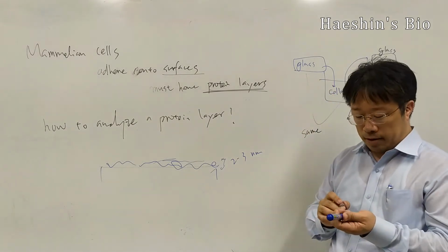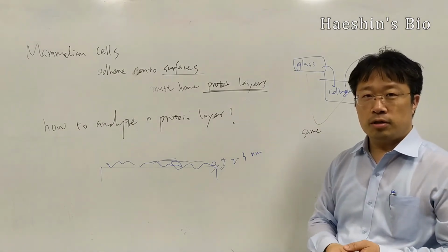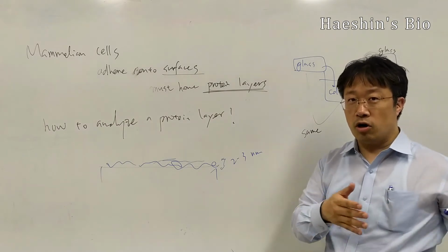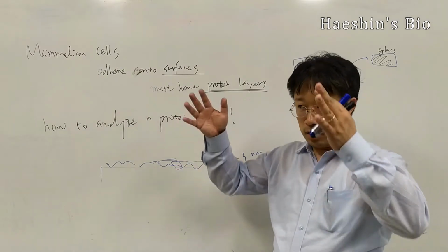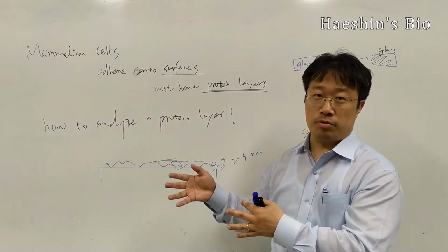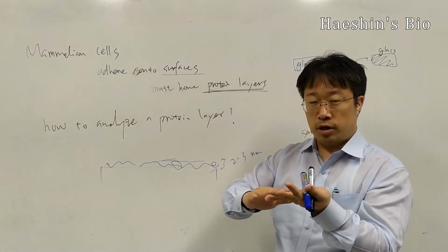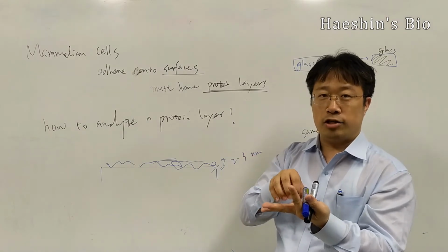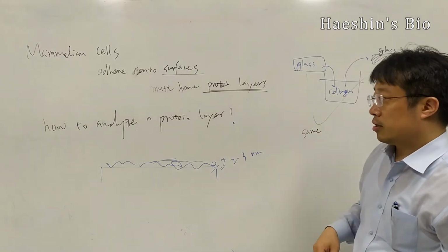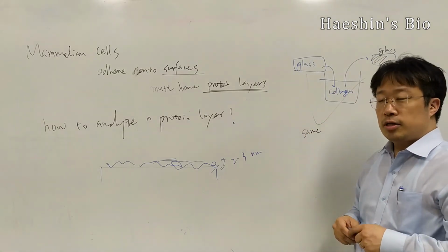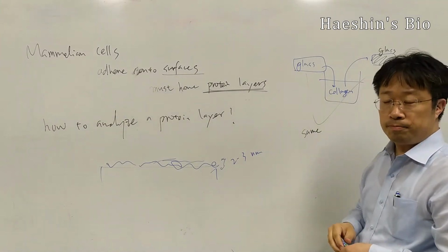So there's the question: you have two pieces of glass, one uncoated by protein, one protein coated. How can you distinguish? The answer might be based on your knowledge: you put them into mammalian cell media, of course without serum, because serum has protein. So in serum-free media, one surface has protein adsorbed, so mammalian cells can attach, adhere, and grow. The other doesn't, and the cells don't recognize it. But this is not chemistry; this is a biological way to distinguish surfaces with or without protein.